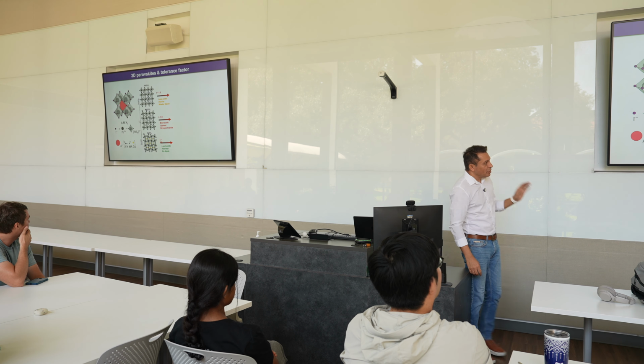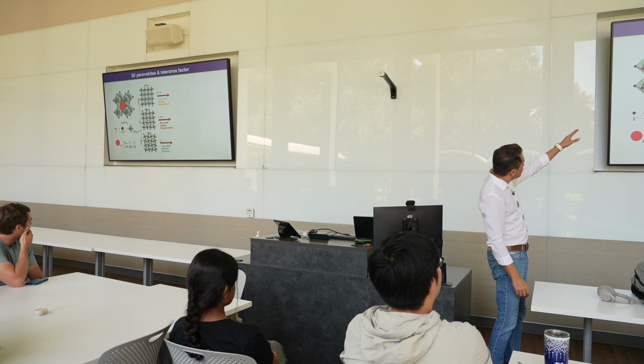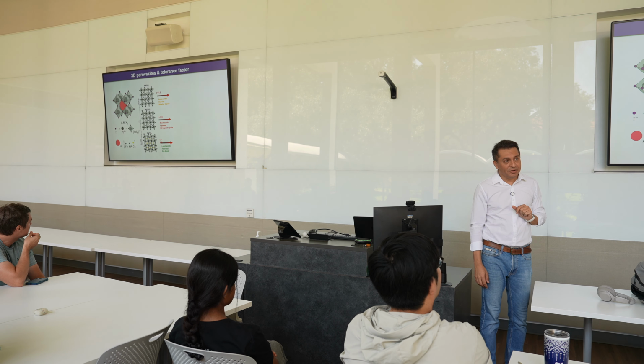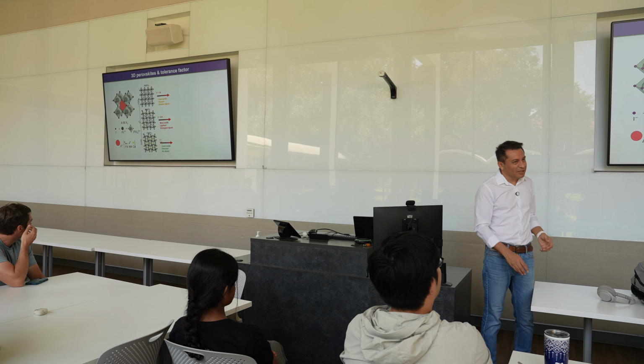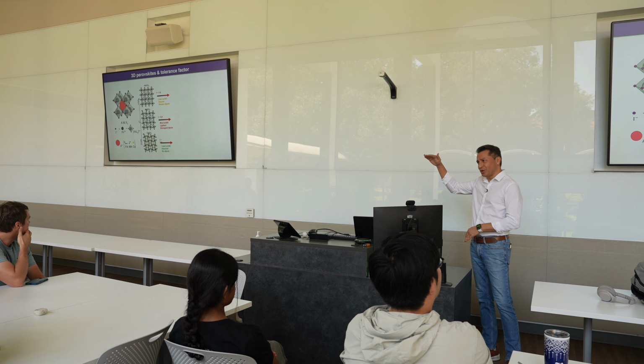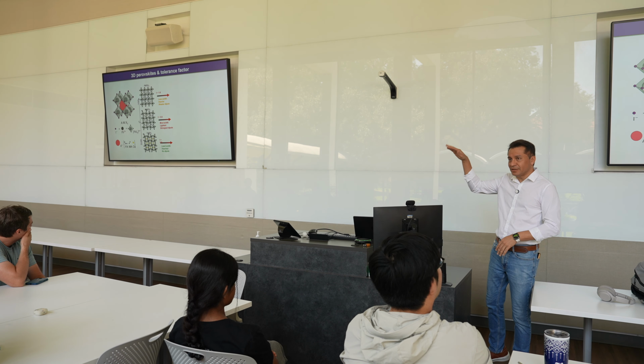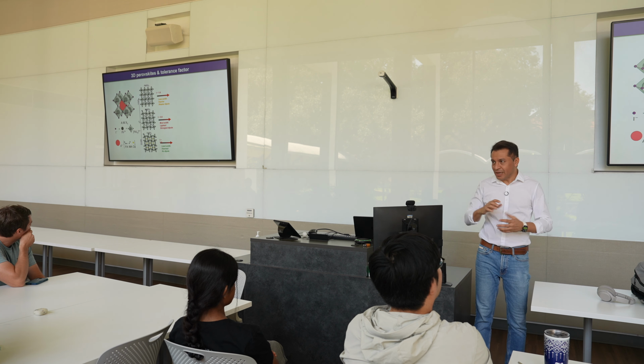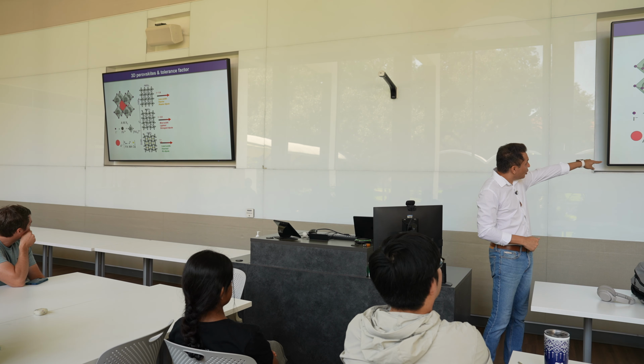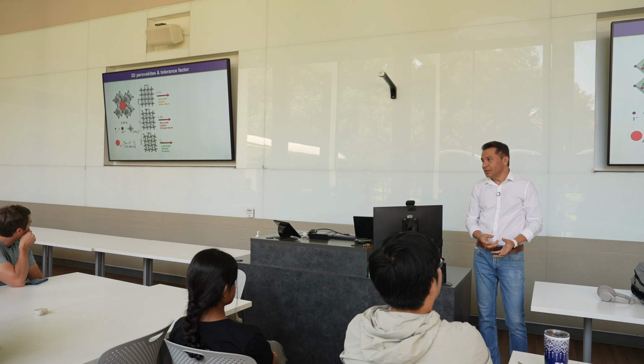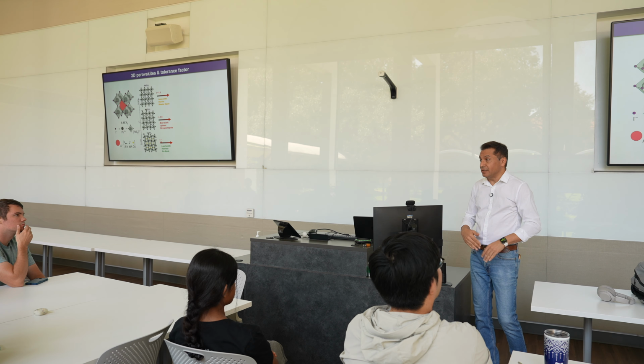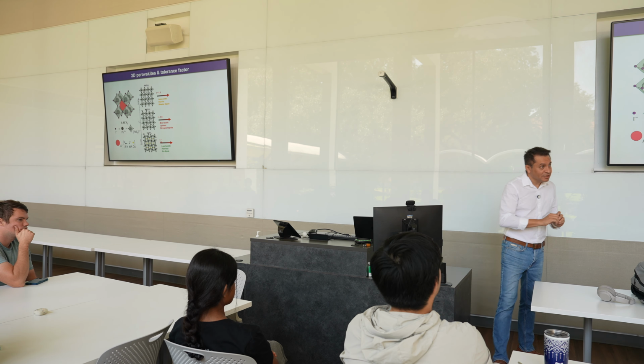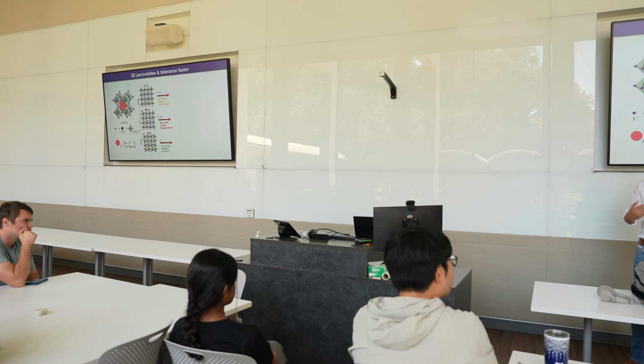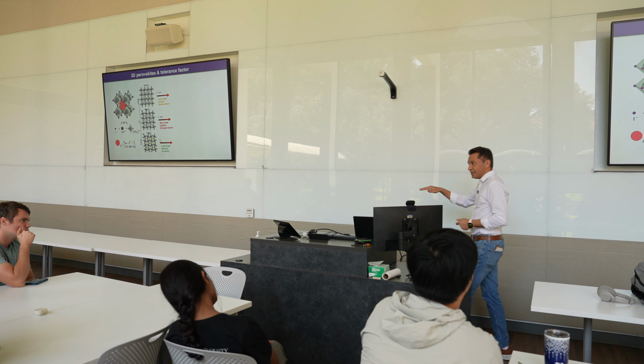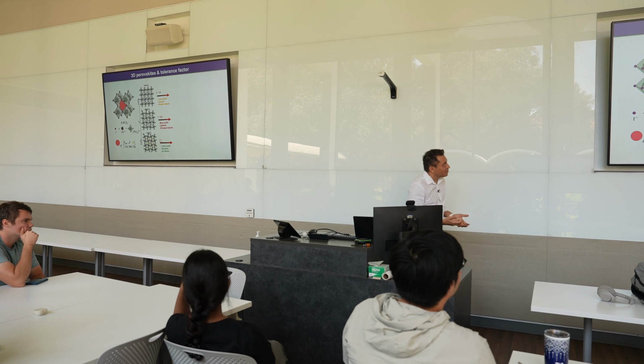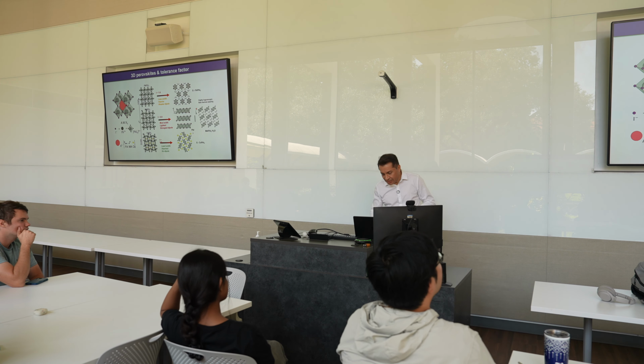So if I take the three simplest ones, this first one is formamidinium lead triiodide, right? I put the FA cation. It has a tolerance factor of almost 1, so it's right on the edge of what you can make, right? It's a little bit bigger, okay? So it's a bit fat. If you look at the bottom one, that's cesium lead iodide, cesium small, right? And so it forms a perovskite that is 0.8. That's on the other extreme, right? So it's really small, right? And methylammonium is perfect. It's right in the middle, right? It's 0.9.